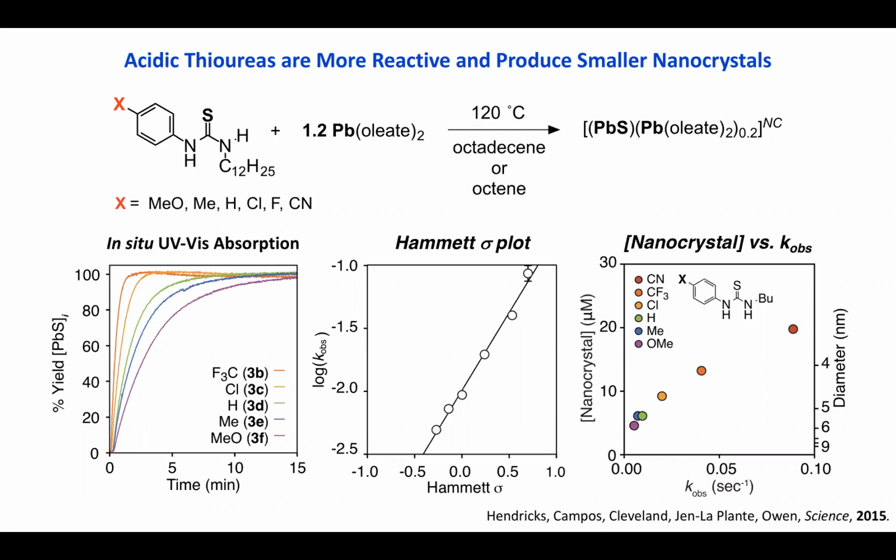That's actually size dependent. So if you want to make a really small crystal, you actually need more lead oleate because the surface area to volume ratio is higher. So you can set the amounts of these as you like, let them react, and then we monitor the formation of lead sulfide using a dip probe. You can stick an optical fiber into your solution and measure the amount of absorbance that way and determine the